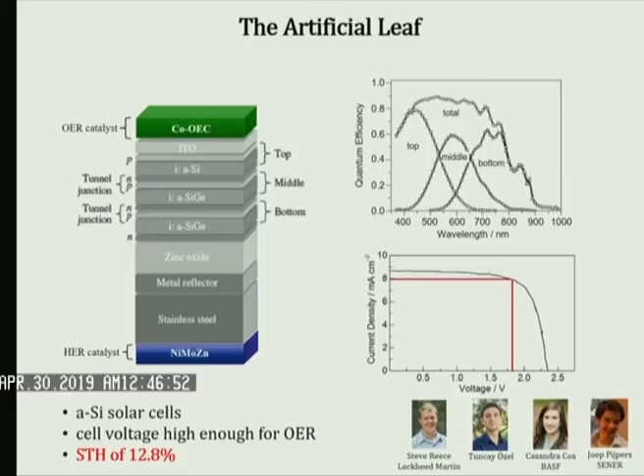And these are the absorption profiles of the top piece of silicon, the middle piece, and the bottom piece. And you can ask, why did we dope so much germanium? How did we know when to stop doping? Because if you take this thing, it now absorbs light, and it absorbs that plus that plus that. So that's the total absorption profile. And that perfectly matches the solar spectrum. So with these 3 flavors of silicon, I catch every photon coming out of the sun.